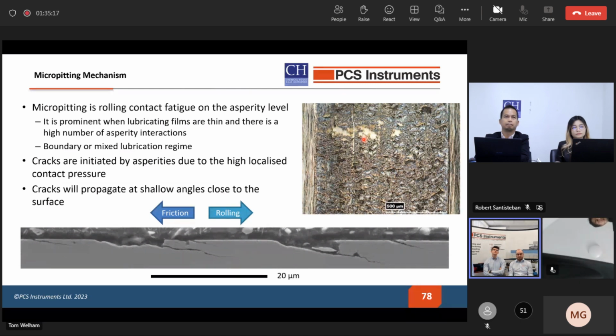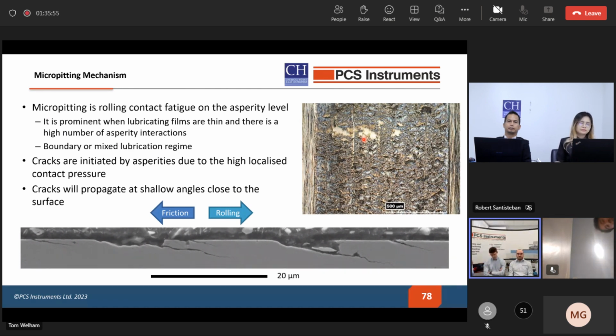So the mechanism behind micropitting is surface fatigue. It happens very close to the surface, and it's fatigue on the asperity level. So it's caused by the surface roughness. This is mostly common in the boundary or mixed lubrication regime. So the surface roughness in contact forms these very high stresses very close to the surface, and the cracks will propagate in the opposite direction to friction. Many cracks are formed, and these cracks will interact with each other in a very complicated way, which is very hard to model. And small bits of material will be ejected continuously as the process goes. So we end up with lots of material loss due to micropitting.